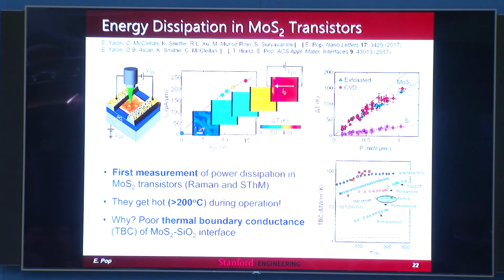And so ever since we've done this, I've realized that actually all the IV data, especially the high field IV data we had taken earlier, probably needs to be maybe slightly reinterpreted, because by the time that you get up to high field, your device is no longer at room temperature. It's actually probably at about 200 Celsius if you started at room temperature, right? If you start at 77 Kelvin, then it's probably at room temperature by the time it heats up. So it's good to know. And if you look at these papers, you can see how to calculate this without actually doing the measurement.